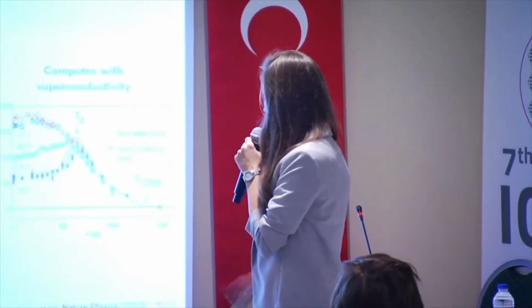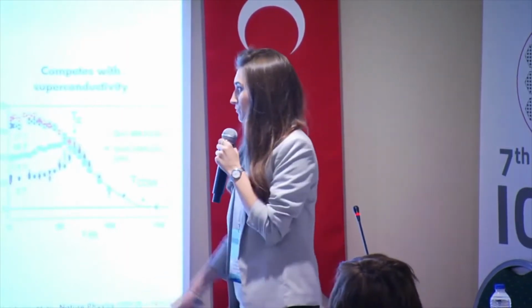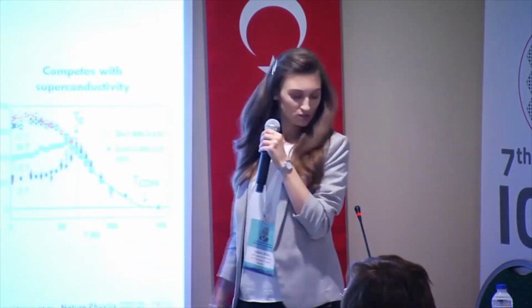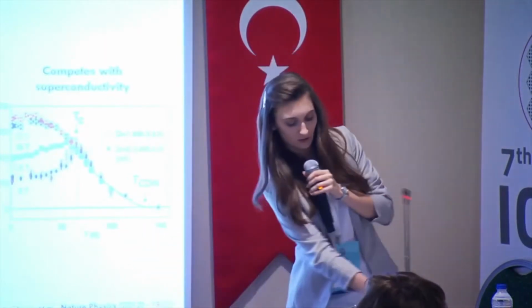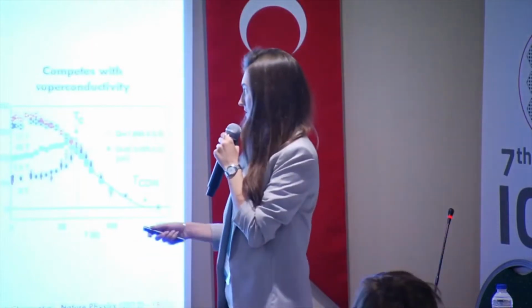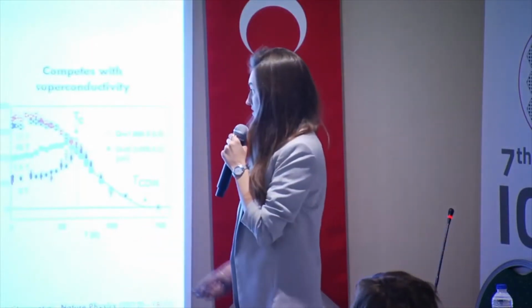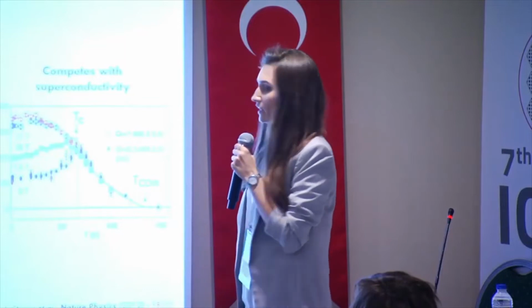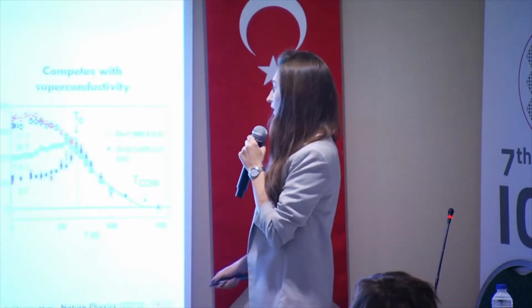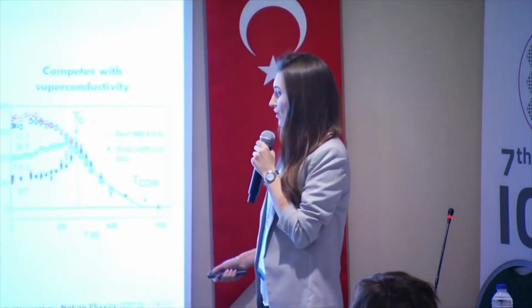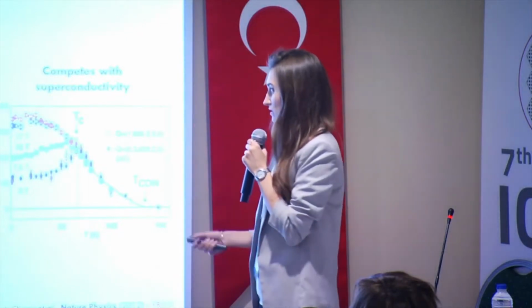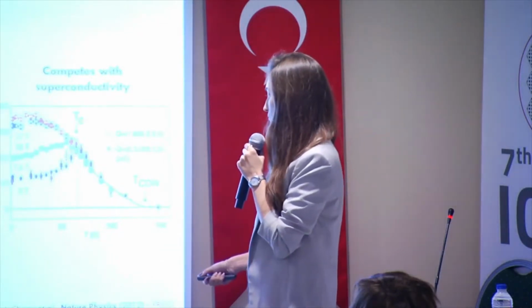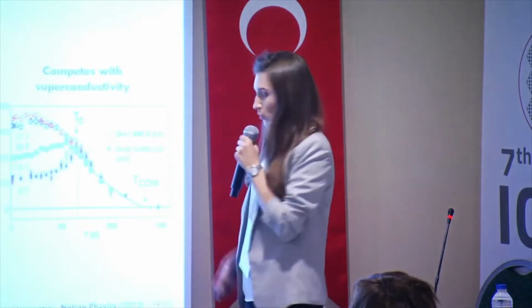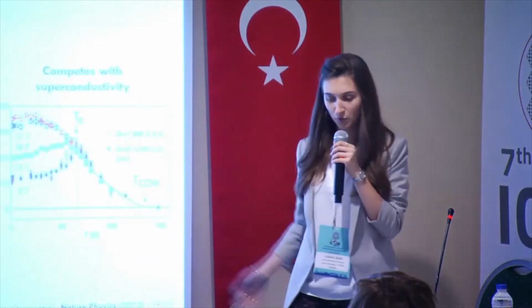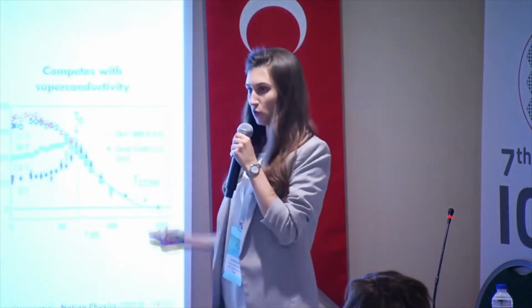So let's start with charge density wave order. It's a charge order which coexists with superconductivity within copper-oxygen planes. It is an incommensurate charge order, quite well defined. For example, we defined the temperature and doping dependence of this charge order for a simple mercury 1201. It was observed in many cuprates, so it's quite a well-known phenomenon.